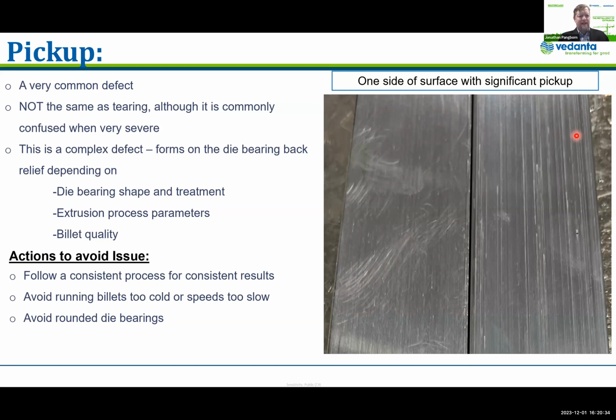It's a very complex defect, but fundamentally it's forming in the die as you're coming off the die bearing, and we'll have a diagram in a moment here. And it's sort of spalling off, and in fact sometimes you can see this type of pickup here that is very lightly sticking, and more than likely you could actually brush that off with a gloved hand or a little piece of cloth or something, and that would fall right off. It's very weakly adhered more than likely.